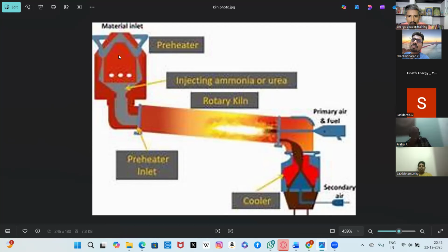Here, the major heat treatment and calcination process is important for us, where we have major coal consumption. Nearly our coal is supplied as G9 to G10, which has a gross calorific value of 4,500 to 4,800 kilocalories per kg of clinker. Because 4,800 is a high calorific value, with lesser calorific value our consumption is more.